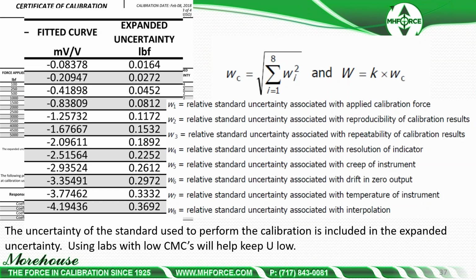And if we start looking at expanded uncertainty, so this is the 5,000 pound cell we did, the points, millivolt values, and you can see the expanded uncertainty of this cell ranges at that 100 pound 2% first test point at 0.0164 to at capacity 0.369. So if we're calibrating expanded uncertainty in accordance with the ISO 376 standard, there's 8 things that we must consider per the standard. There are additional things to consider, certainly, but there's 8 that are built into it.